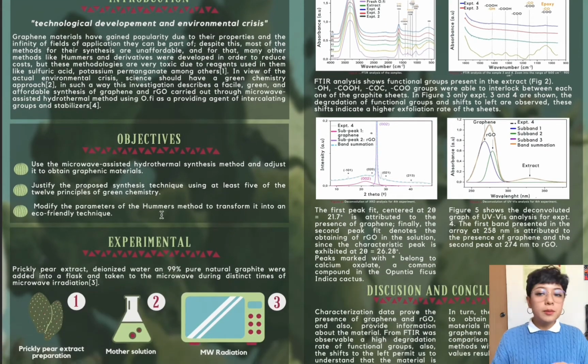Okay, before we continue with the experimental part, in a simple way I want to explain how Hummers' method works. In an acid medium, graphite sheets are immersed in order to begin to separate one from the other. Then, when we add an aggressive oxidant, we obtain graphite oxide. Oxygenated groups begin to intercalate themselves into the sheets, increasing interlaminar distance, and as a result, we obtain graphene oxide. The graphene oxide is washed and treated with an ultrasonic bath to eliminate the remaining functional groups and isolate graphene sheets. From this, we can understand the Hummers' method requirements. We need a strong acid and an aggressive oxidant.